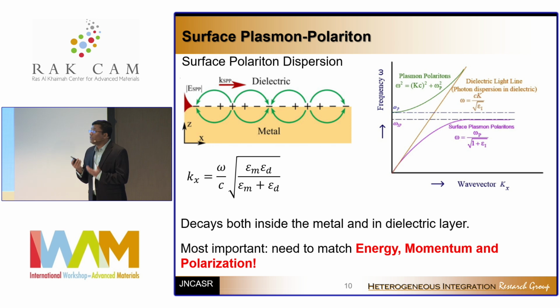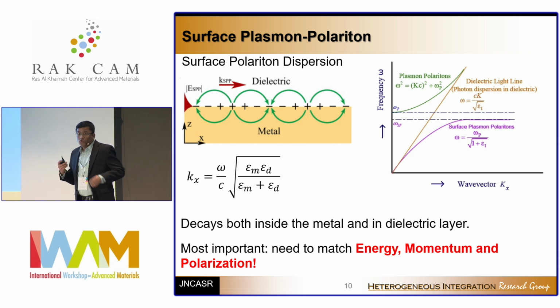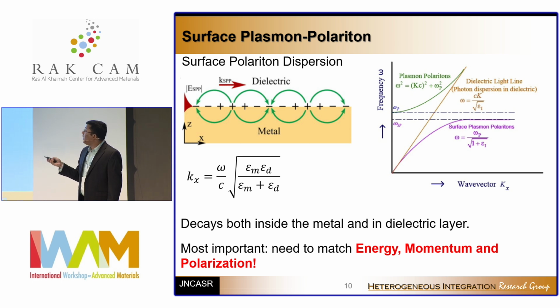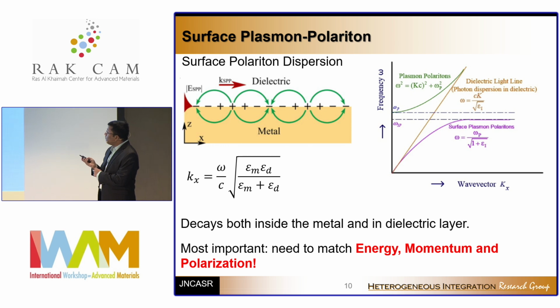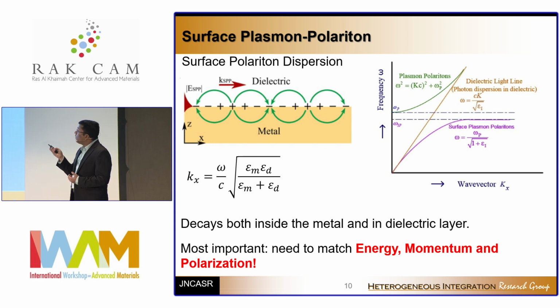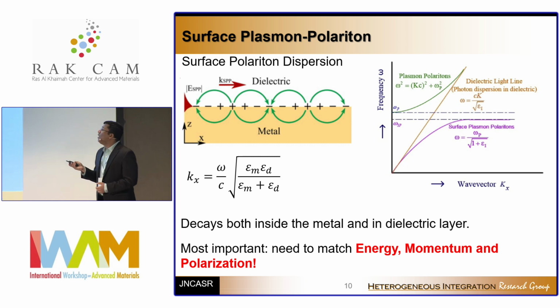Now, just like you can have electrons in a volume plasmon excitation, you also have electrons on the surface of the metal. And if you shine light, and if you are careful that you give enough momentum to this, because the surface Plasmon-Polariton band basically lies to the right side of the light cone. So basically, you need an extra momentum for light to couple with the surface polaritons. Basically, you can then also excite the surface Plasmon-Polariton modes.